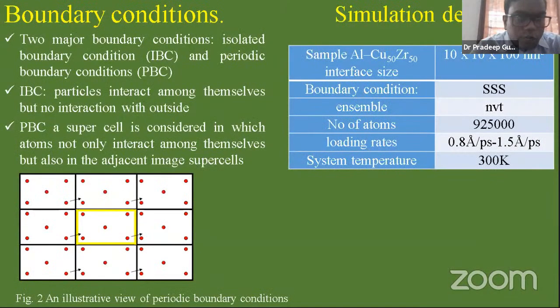The boundary condition we are using here is SSS, and this is the sample and this is the ensemble. The number of atoms we are using here is 925,000. The loading rate is 0.8 to 1.5, and the simulation temperature we are using here is 300 K.